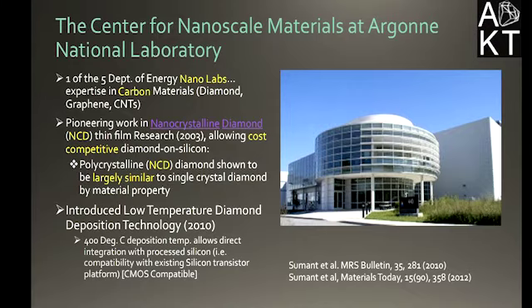And their pioneering work in 2003 actually produced nanocrystalline diamond, or diamond on silicon technology, which for the first time we can now incorporate diamond on silicon where we didn't have to have an entire diamond substrate. So the cost was removed from it, and we can actually do it in a larger area. But again, temperature was the issue.